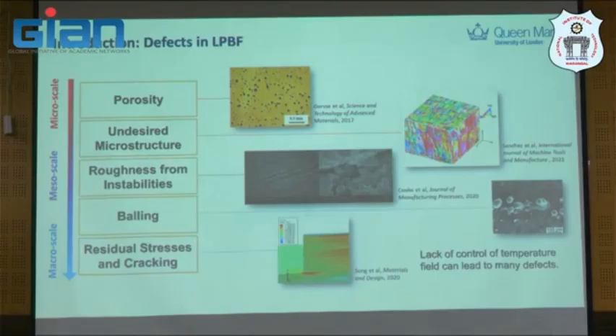So what shall we do? That is the next question. Microstructure as well is in the scale of 10 to 100 micron. Roughness is also in that micron scale, which is lower than 1 millimeter, I believe, apart from the residual stress or balling effect, which is actually larger than the typical mesh size for finite element calculation.